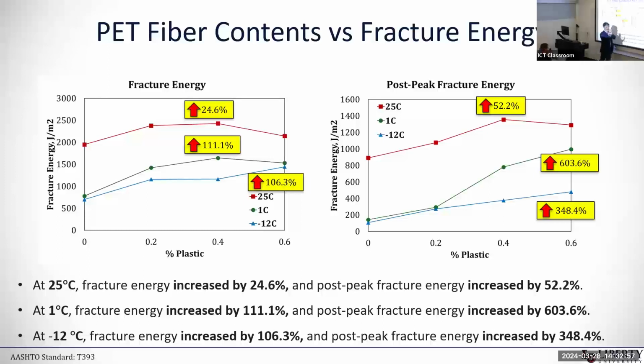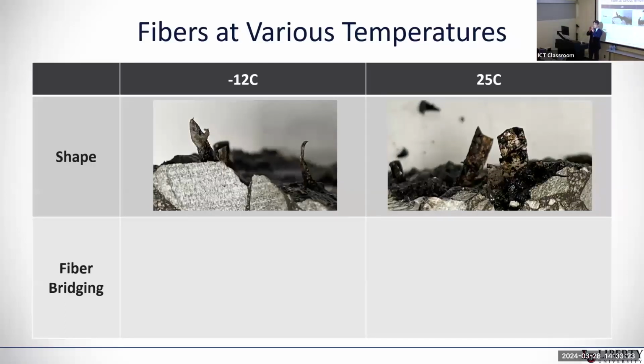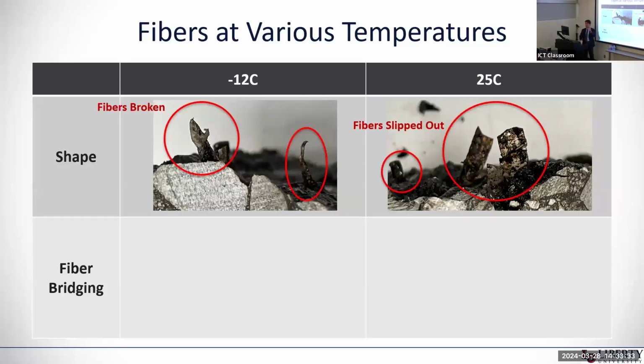When we zoom in on the post-peak fracture energy, as we add more and more plastic, it continuously increases the fracture energy, except at 25 degrees C. So there's a question mark: why do we have different behavior between 25 degrees C and the low temperature? So we looked at the fiber failure side. At the low temperature, when you look at the fibers here, there is a sharp end, which means this fiber was broken during crack propagation. The fiber holds this material together, and then it actually breaks when the crack is forced to propagate.